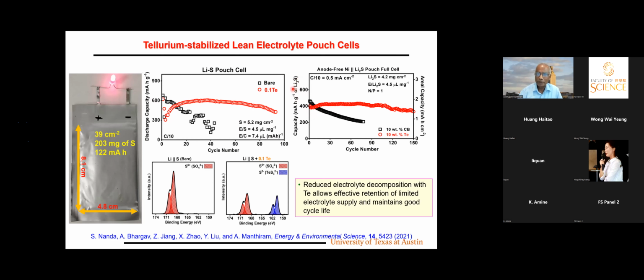So, I just want to point out, this is per gram of Li2S, that's why the value looks lower. But obviously, the most important point is the cycle life. Tellurium addition changes it, and that is because without any tellurium, you have more oxidized species. When we add tellurium, because of the formation of the Li2TeS3, we have better cycle life. We have also done modeling with tellurium, selenium, and without any of those additives. Clearly, the Li2TeS3 formation provides better lithium diffusion pathways with lower energy barrier. That's why the lithium is able to diffuse through that much easier, keeping better cyclability.